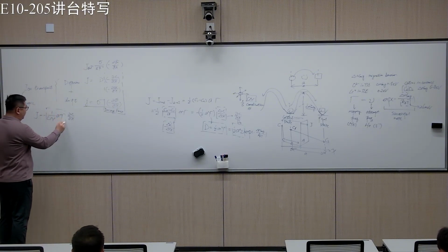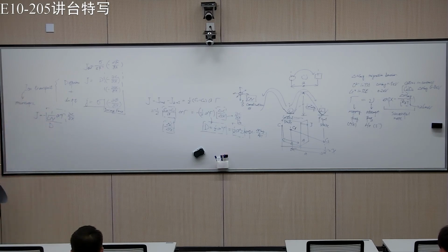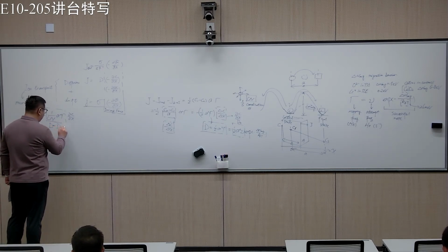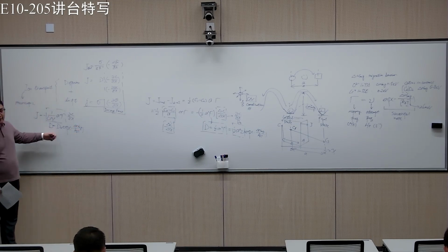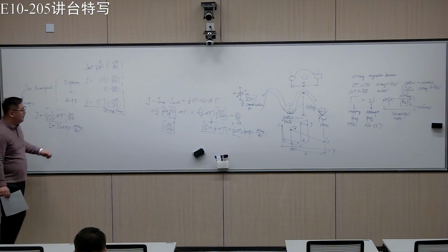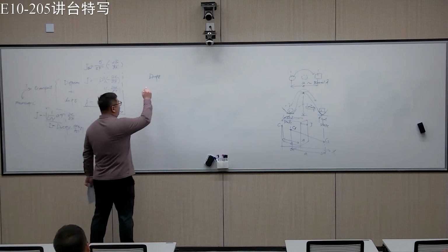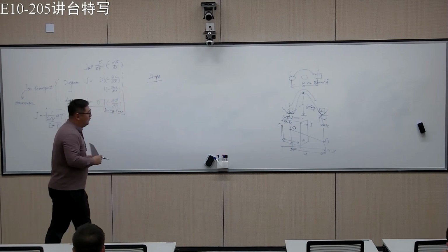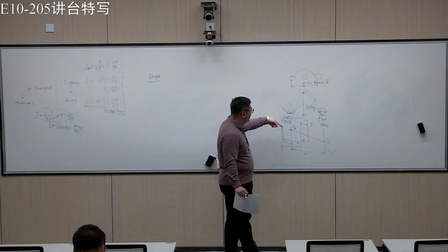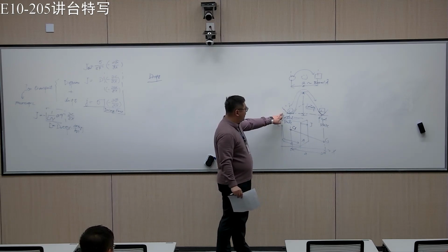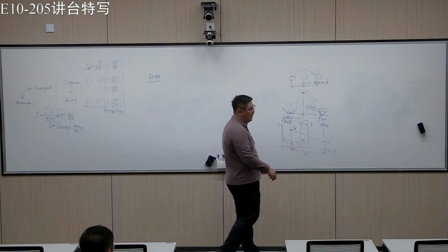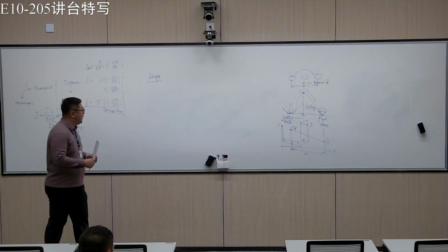So this is basically the diffusivity, and we know that diffusivity is activated and limited by the hopping or the migration barrier. The second thing we want to talk about is the drift. For diffusion, we have this kind of picture: an initial state and a final state, which are essentially the same. The level for the initial state and final state are on the same level because they are just two sites in the atomic structure.